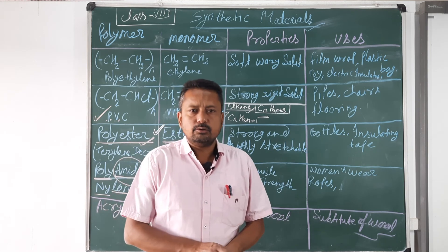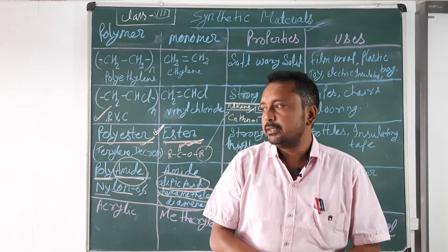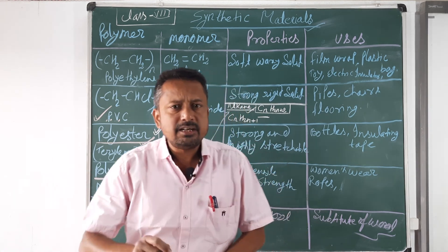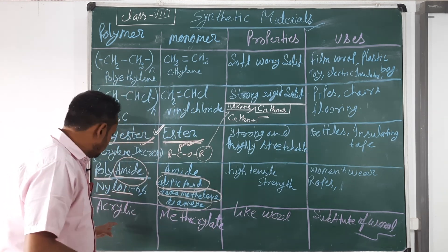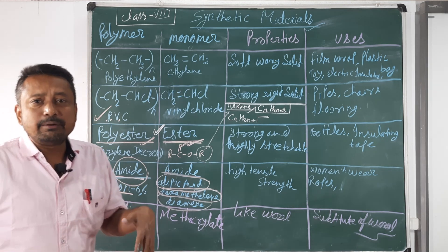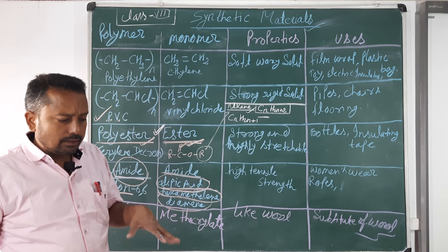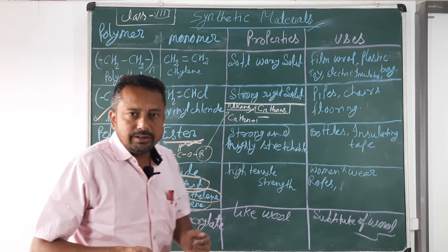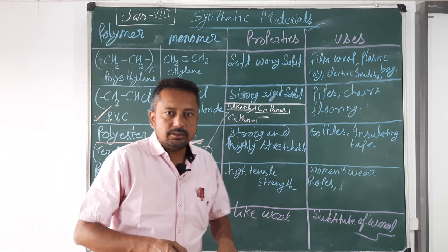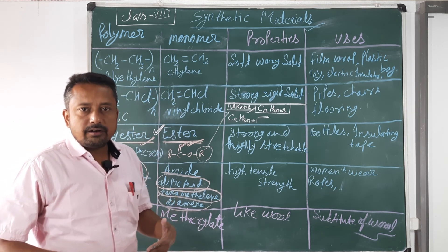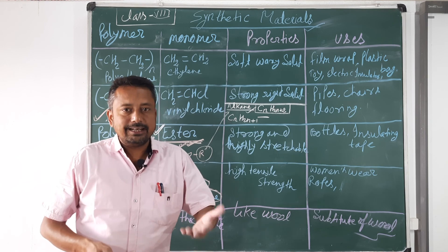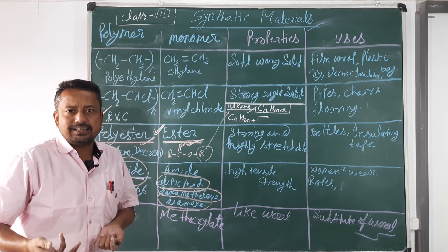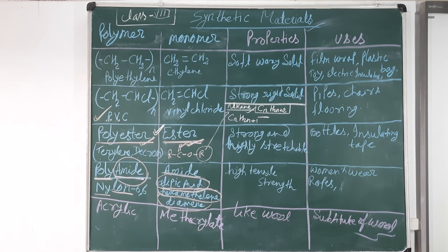There is a simple way to identify the difference between acrylic and natural wool. If you combust natural wool, it burns directly without melting. But when you burn acrylics, it melts before burning. So you can easily identify whether a given fiber is acrylic or natural wool simply by burning it, since synthetic wool melts before burning while natural wool burns directly without melting.